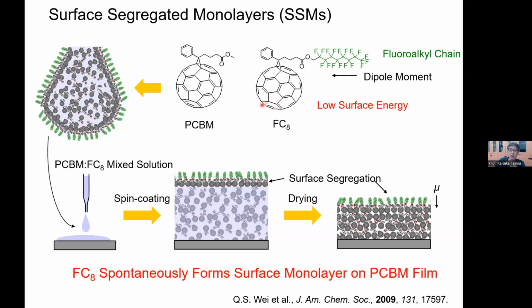What happened here is that this is PCBM, an organic semiconductor. It's not a polymer, but a small molecule. And we developed a similar type of semiconductor with a fluoride chain attached. This fluoride chain is known to have low surface energy, much lower than the others. So it acts like a surfactant in the organic solvent. We mix two components together in the solution, and these surfactants cover the surface of the solution, right?